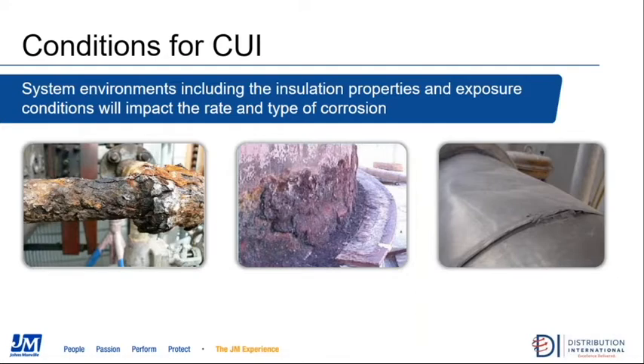So as I said, there are concerns about the introduction of contaminants either from the environment or possibly from the insulation material itself. And those conditions can significantly impact the type of corrosion that occurs, as well as the rate at which that corrosion occurs. You can see some examples of fairly substantial events of corrosion in these pictures, as well as some damaged metal jacketing over the insulation, which is one of the prime conditions we see that allows water ingress to occur in the first place.